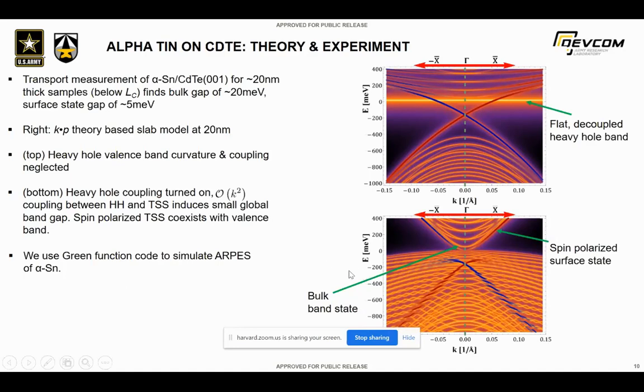And shown here are some interesting slides where he uses the fact that you can decouple the heavy hole band structure, to make it simple to avoid seeing the band hybridizations in the heavy hole band, which complicates and makes it hard to interpret ARPES measurements. But basically you can see there's a whole bunch of band structure details, especially heavy hole details in the valence band, which tends to make it hard to see the Dirac point or the crossing of an identified Dirac point. But the key point is that you can use theory to simulate these ARPES measurements.